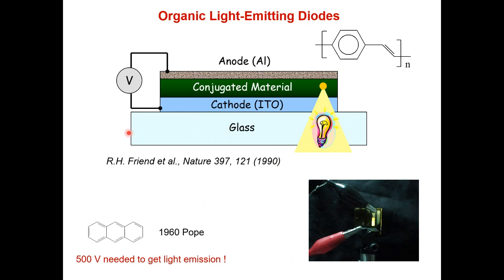So it's a simple device. You take a glass substrate, you deposit ITO. ITO is a very specific material. It's transparent and metallic. Then you deposit a conjugated material, like a polymer chain, a conjugated chain, and then you evaporate a small metallic contact. And if you apply a bias between those two contacts, you get some light coming out from the organic material. And this is the beginning of what is known now as the OLED technology. So it's an organic-based light-emitting diode.